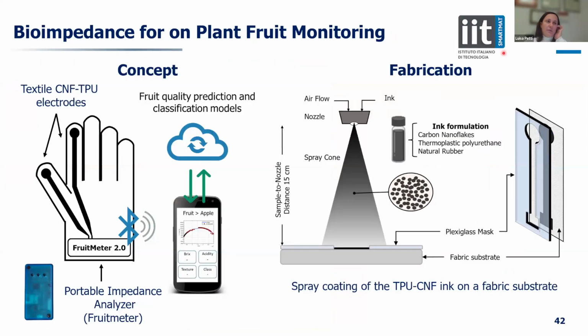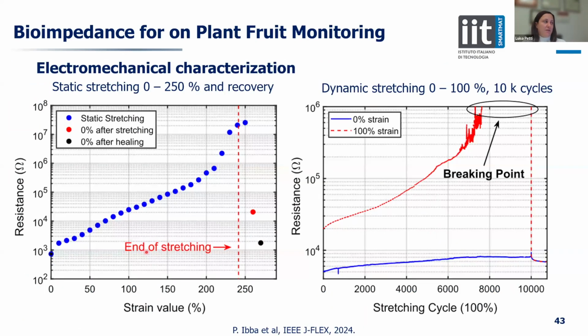And this was again in collaboration with the Smart Material Labs at the Italian Institute of Technology in Genova, where we developed a textile glove integrating a portable impedance analyzer. This is a perfect example of hybrid electronics because this is standard electronics, spray coating TPU carbon nanoflakes on a fabric substrate.